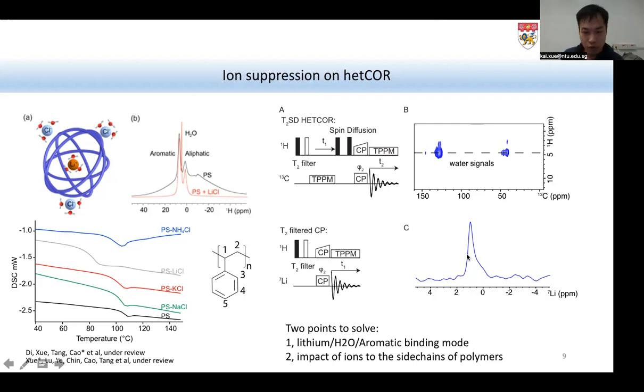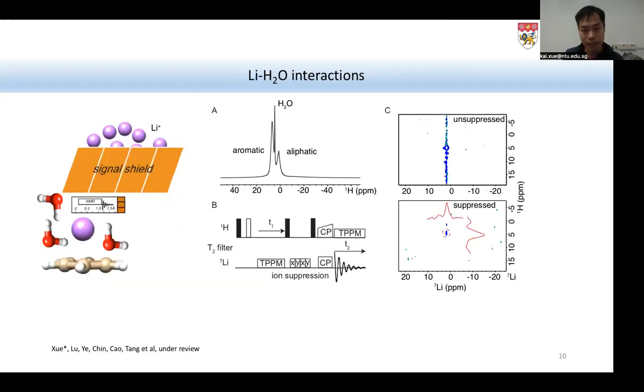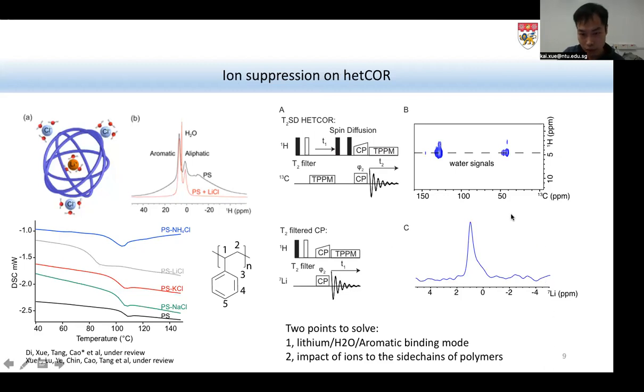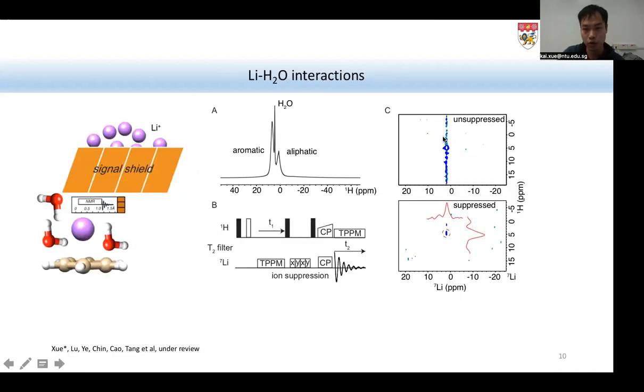When this work comes to this point, we still have two points to solve. One is what the binding mode for lithium to water is, and also, since the glass transition temperature of polystyrene has changed, does the ion really have an impact on the side chain packing or dynamics of the side chains in the polymer? So we continue this study. In this spectrum, with the CP transfer from protons to lithium, we observe a signal. But when we try to detect this signal in 2D, we found that the peak is half real, half fake, because obviously there are excess ion signals in the system, and these ion signals escape the phase cycling and give rise to T1 noise in the spectrum.